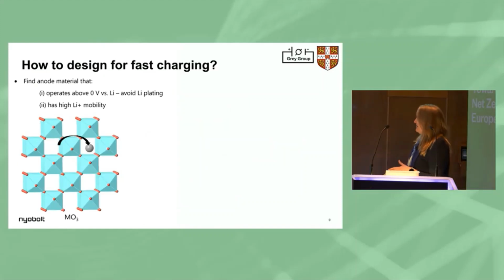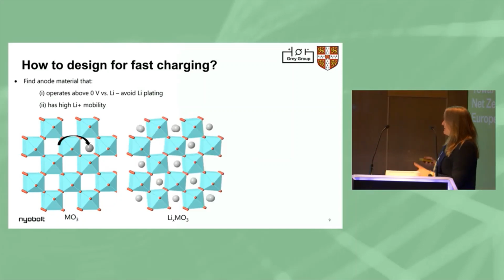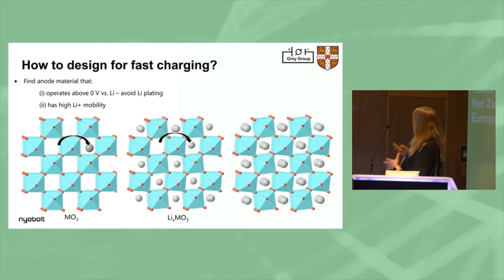So Claire, Kent and others in Claire's research group have done a huge amount of work looking at finding a new material that enables fast charging from the anode perspective. So really looking for an anode material that operates at a higher voltage than 0 volts, so avoiding that lithium ion plating, and has high lithium ion mobility. So an example of a structure looked at is a perovskite structure, where the lithium ions can jump into the different channels. But as you start to fill up the structure, then you get distortion, and you end up with the ions essentially getting stuck.